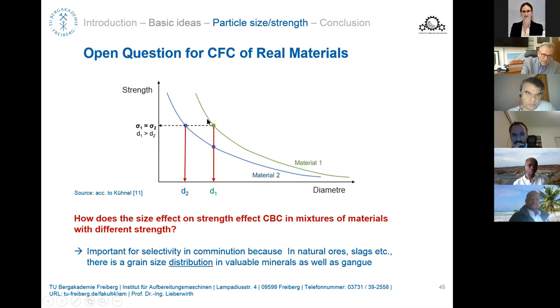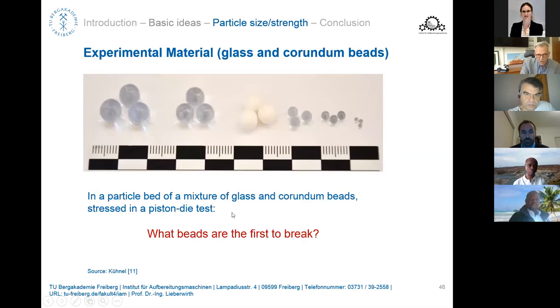Essentially, the approach was that we looked at two materials, this is the typical Bond curve, or whatever you call it, strength versus diameter, for the two materials, and we looked at what sizes the two materials would exhibit the same strength. So we did it. We started with the tests with a combination of glass beads and corundum beads.